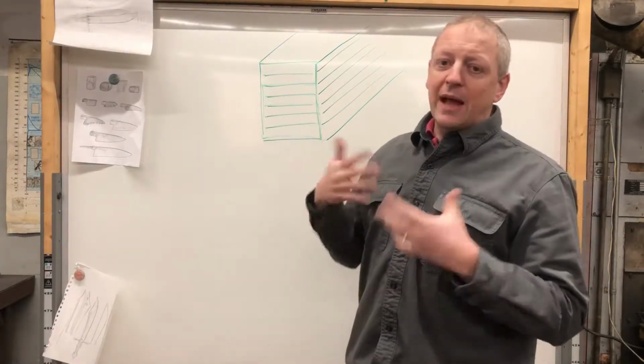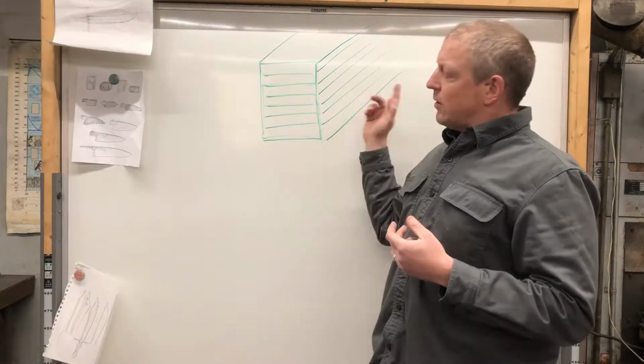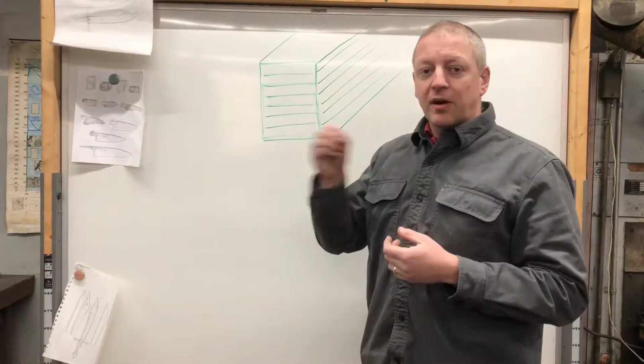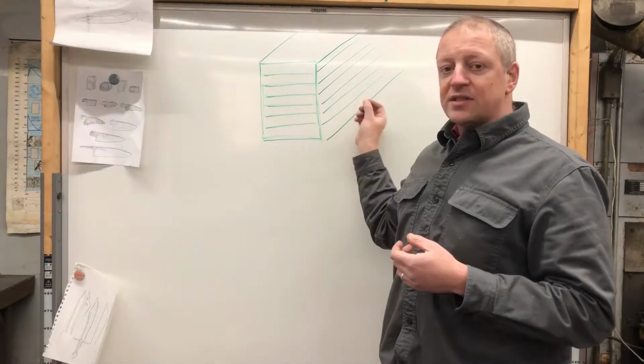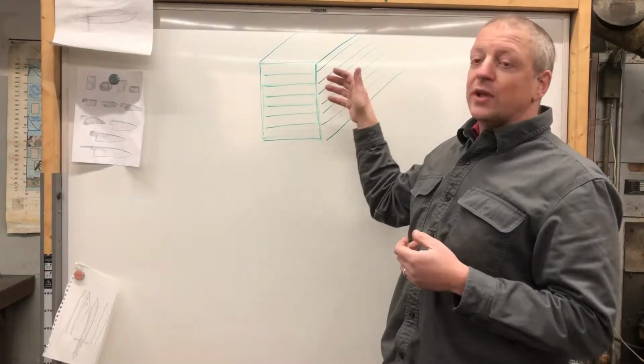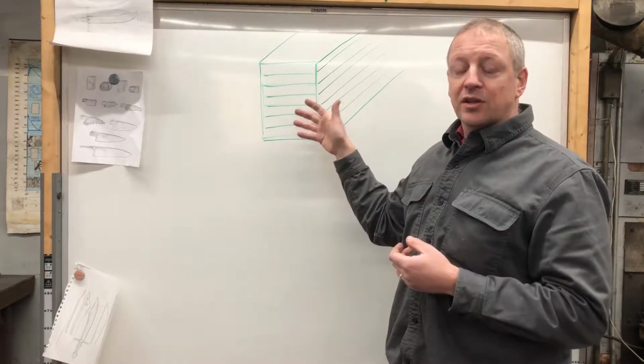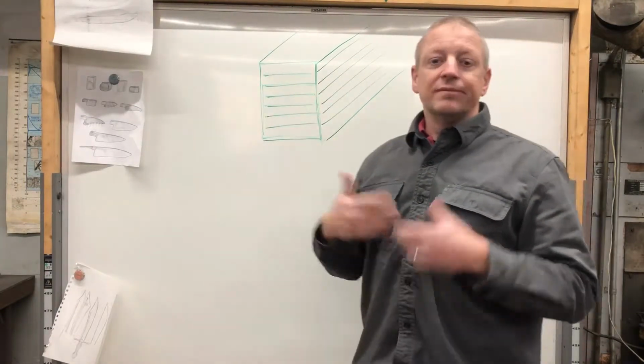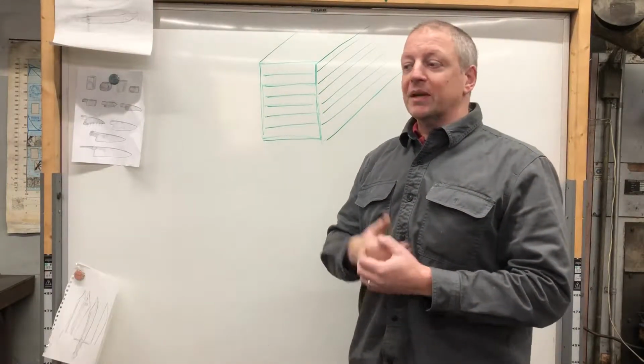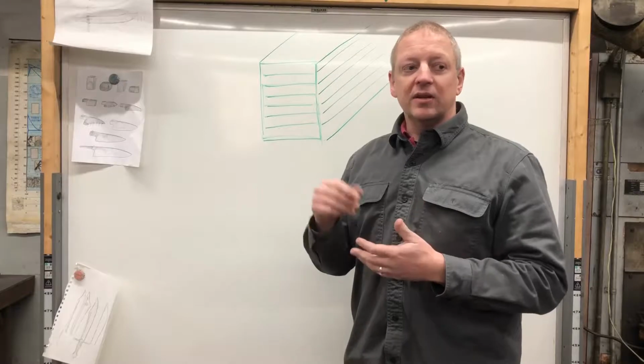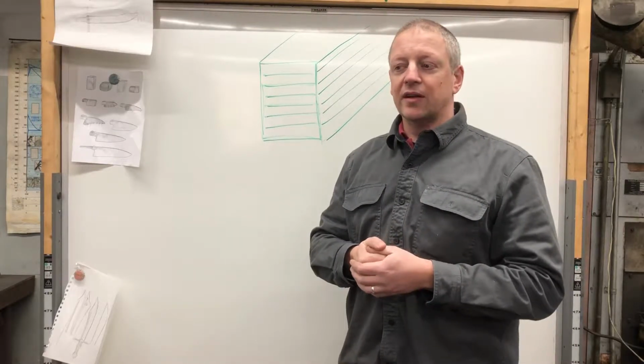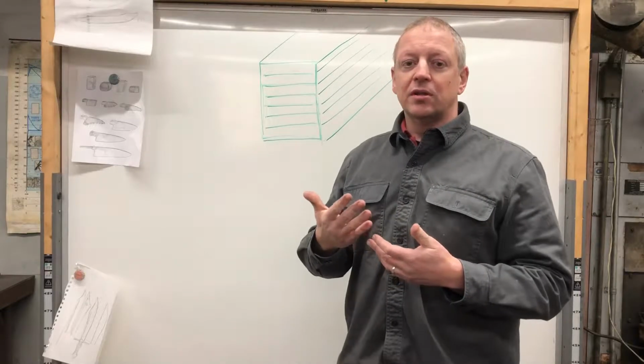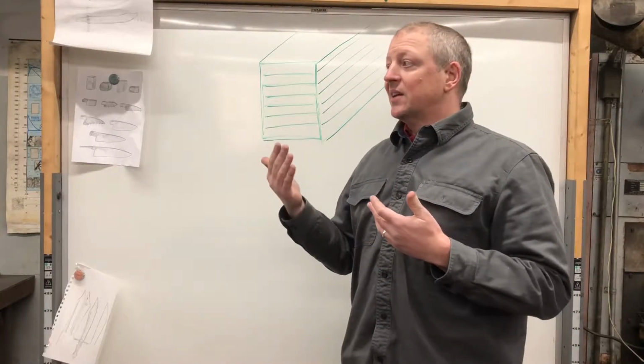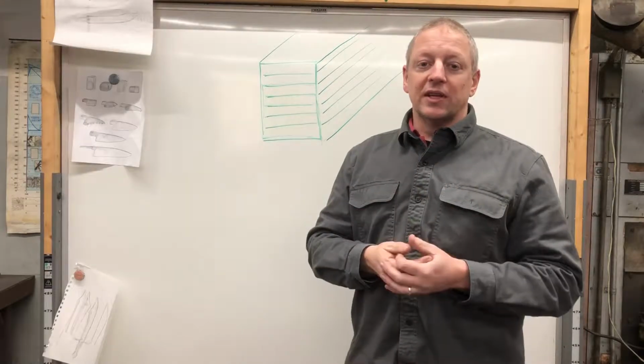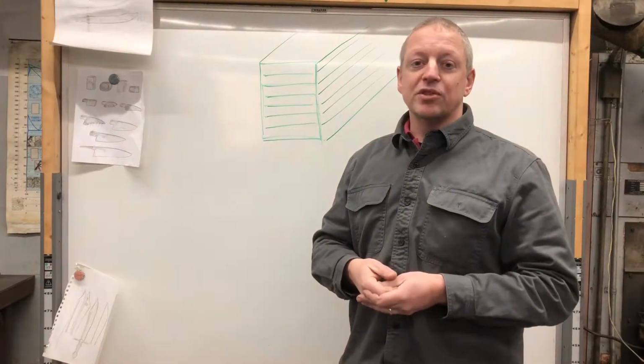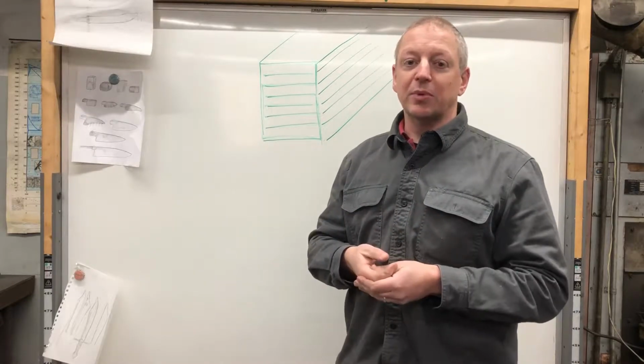Because of course, if we're doing atmospheric welding, the dry welding, we're not welding up all these seams on the sides. We're not arc welding those or anything. They are not sealed. So theoretically, you can continue to get oxidation along the edges, no matter what. Your forge environment is not perfect. Even if you tune it down so that you've got a gas-rich environment in there, you still almost certainly have free oxygen floating around just because your burn's not going to be perfect.